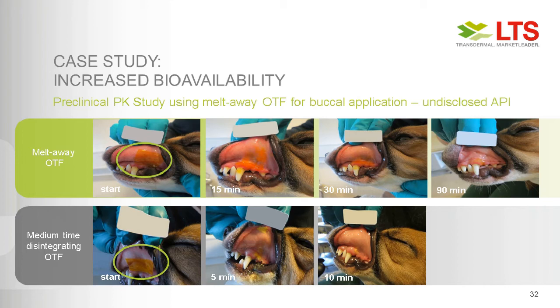It forms a mucoadhesive gel, which you can see here in the pictures, the orange film, which is applied. After 15 and 30 minutes, you still see the remaining gel with the orange color, the orange dye in here, which remains in the cheek of the dog. So after about 90 minutes, all of the orange color is gone, all of the gel disappeared, and the dogs were not sedated, so they could also lick at the film. So you can see how well these melt-away films adhere to the buccal cheek and cannot easily be removed